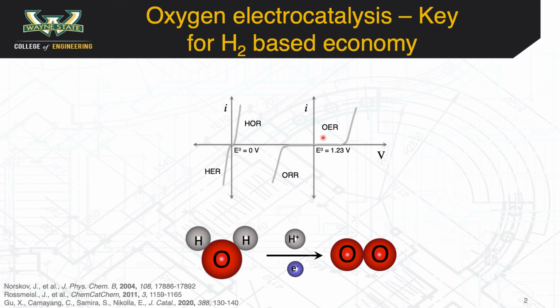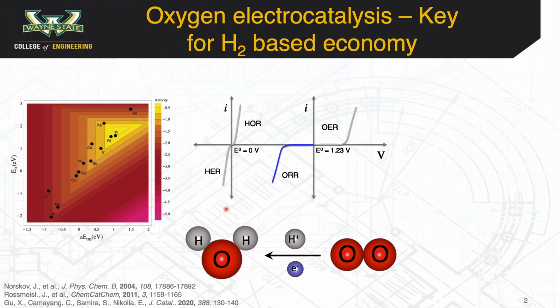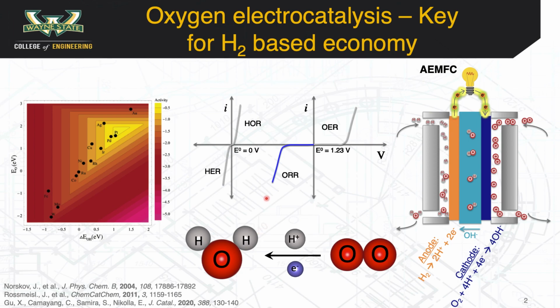What can then be done with the generated hydrogen and oxygen is that they can be recombined in a fuel cell, leading to the formation of water. Even during consumption of hydrogen as the fuel, it is observed that oxygen reduction reaction deviates significantly from the theoretical potential as compared to hydrogen oxidation, thus making ORR the overall efficiency determining step in a fuel cell. What is also interesting is that even at these significant deviations from the thermodynamic potential, the best performing catalysts remain noble group metal based catalysts such as platinum and palladium, thus making their commercial realization challenging.